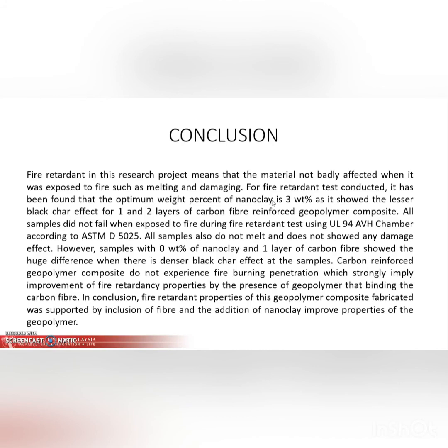All the samples did not fail when exposed to fire during fire retardant testing using the UL 94 AVH Chamber according to ASTM D5025. All samples do not melt and do not show any damage effect. However, the sample with 0% of nanoclay and 1 layer of carbon fiber shows a huge difference, as there is a denser black char effect on the sample.